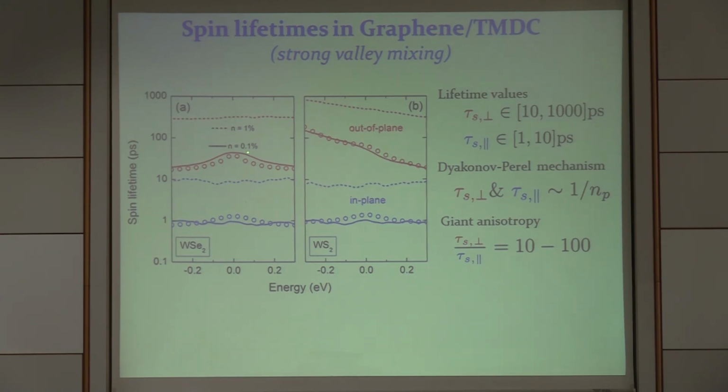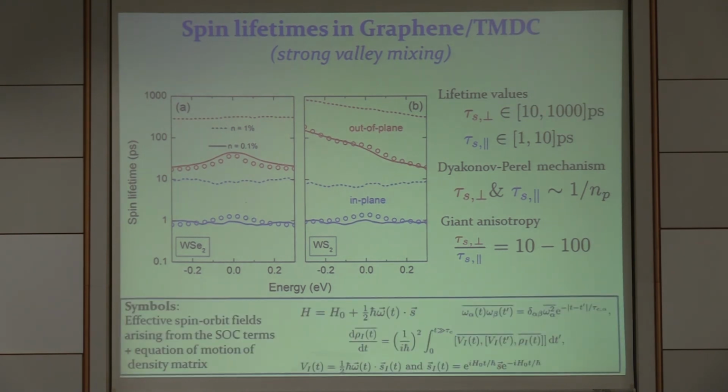So you see that at a certain density of defects or puddles, we get a factor of 10, or we can even get a factor of 100. So this is completely unknown, I mean unprecedented. This type of anisotropy I've never seen in any type of interface. And here our simulation is using the full quantum dynamics, but we also had an effective model that gives this result that perfectly matches. So everything really matched, and we have this giant anisotropy in these interfaces.